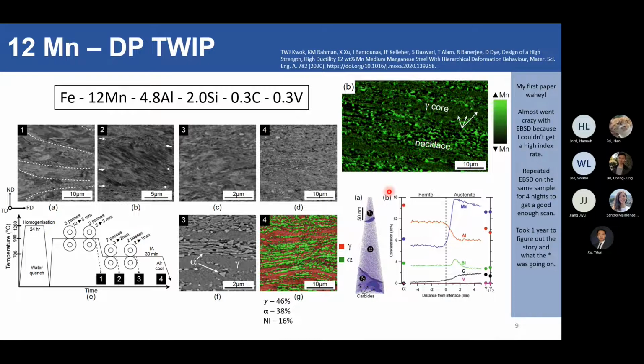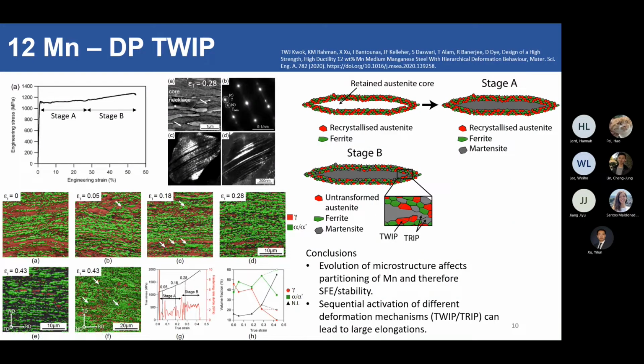And you can see here that the core austenite is actually not very highly enriched in manganese, but the necklace austenite grains are. And that's because by nature of very small grains right next to each other, you've got a very short diffusion distance, so they partition a lot better. So this is an APT needle that we lifted out from the necklace grains, and you can see this is very effective partitioning going on in there. Right, so now we do a tensile test, and we realize that, number one, you got absolutely stonking strength, right? It's more than 1 gigapascal. And you've got more than 50% elongation, which is massive.